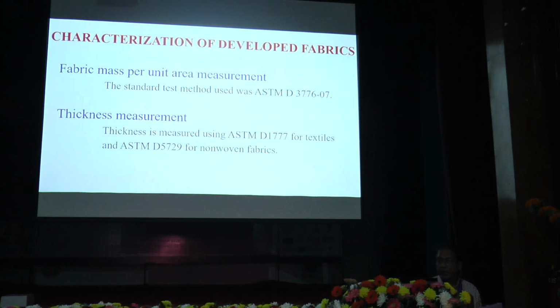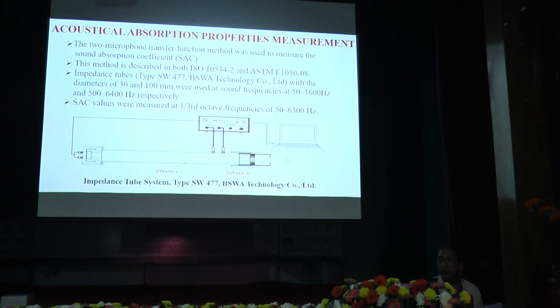Then we have the characterization of the developed fabric, and the acoustic characterization of the textile material, where we measure the sound absorption coefficient, also measured at 1/3 octave frequency of 50 to 6300 hertz.